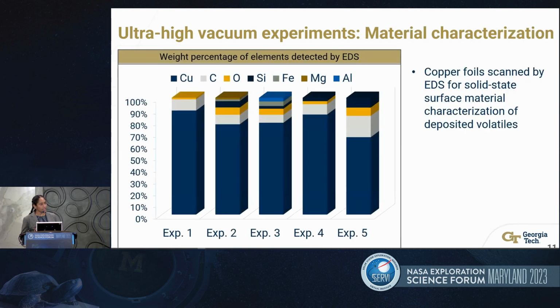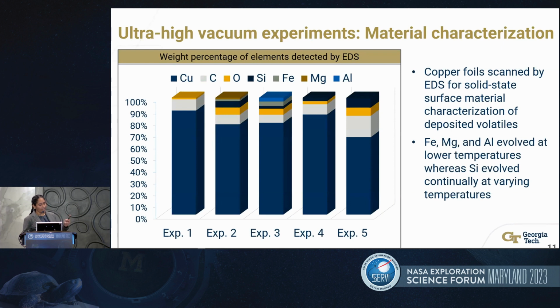So the copper foil that was used to collect the volatiles was then studied using EDS, and the weight percentage is shown in this chart. So the Cu, C, and O are contributions from the copper foil. Results show that iron, magnesium, and aluminum evolved from the sample at the lower end of the temperature range, and silicon continuously evolved during the different temperatures. The changes in the amount of silicon evolving during the different experiments show that different silicon constituents were evolving at